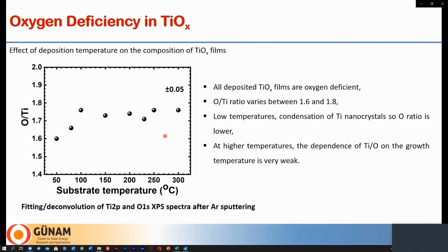One of the important parameters is the ratio of oxygen to titanium atoms in this layer. It gives you the degree of stoichiometry of the film. In this study, from XPS analysis, we have seen that this ratio is between 1.6 and 1.8, and all deposited titanium oxide films are oxygen deficient. At low temperature, we see less oxygen because we have condensation of titanium nanocrystals. At high temperature, the dependence on temperature is quite weak, which may be good for the reproducibility of the film.